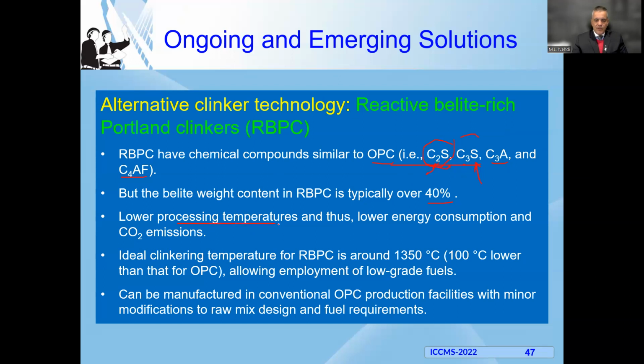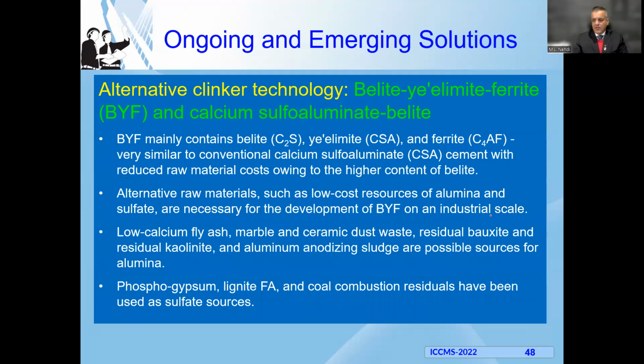But due to the processing temperature for high belite cements, they would consume less energy and they would be emitting less CO2. Maybe we can produce them at a temperature maybe 100 degrees Celsius lower than the normal cements, and they don't require substantial changes in technology. I mean, we can produce them using the normal, existing cement manufacturing technology.